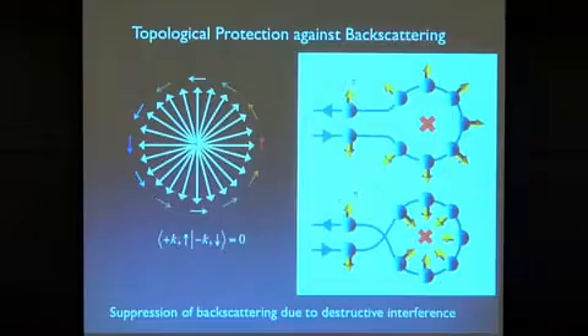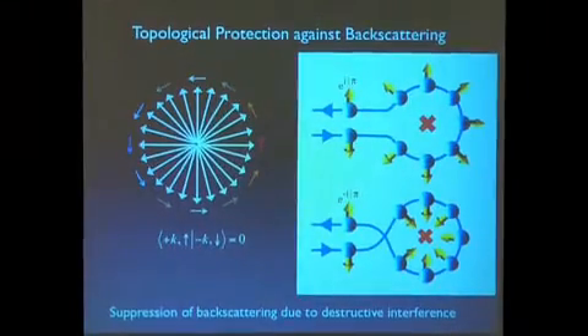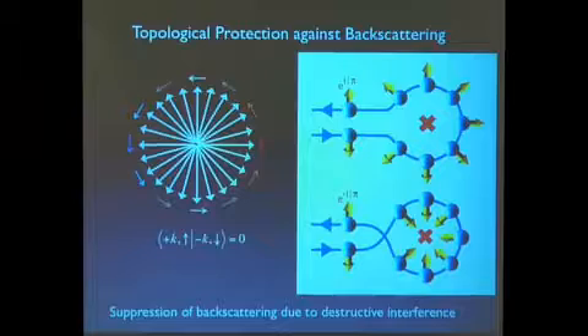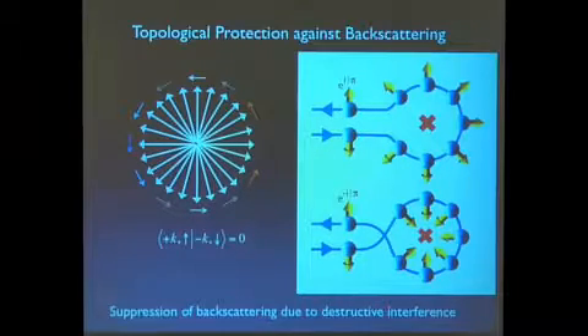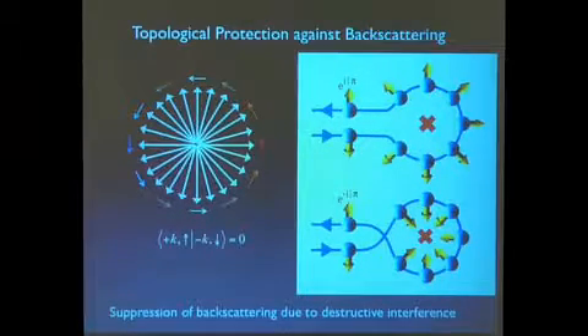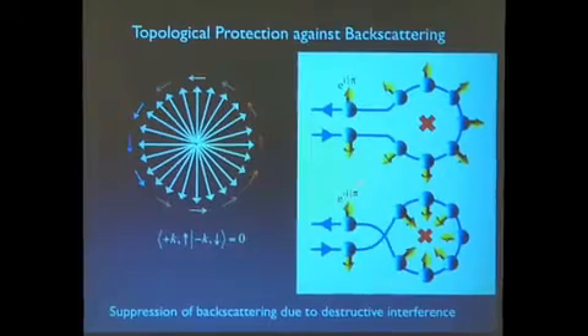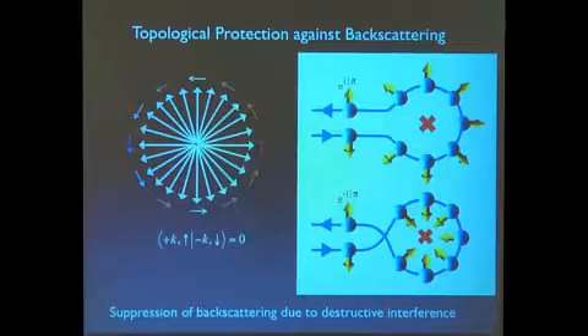Another way to think about this is that if you haven't broken time reversal symmetry, in a system where you have a spin-orbit coupling, when an electron encounters a defect, basically it has two options of backscattering. And these two options have to do with the way in which it brings its spin, if you like, around this impurity when it's going forward to going backward. And these two ways basically give you perfect destructive interference. So this is one of the things that had been predicted out there after the discovery of topological insulators.